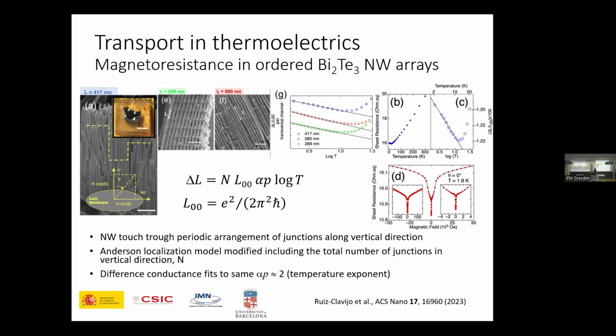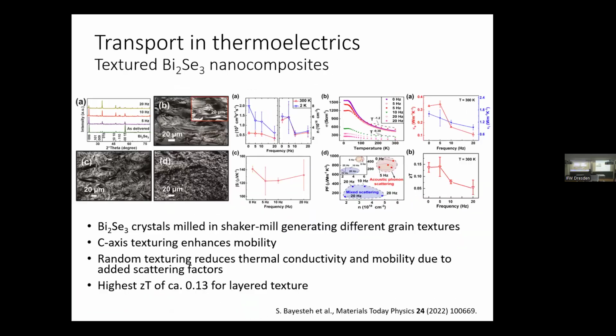And then the more natural question for me would be, if you're speaking again of grains and grain boundaries, what about topological surface states? Yes, complicated. This is not included in here. In this summary, there is some effect. It should be topologically protected. Well, these materials are extremely disordered. So we did not measure flakes of these things; nanolayers have been measured a million times. But nonetheless, it's not presented here. It's measured, I can show you later in the discussion. We can see localization effects in these composites. Localization with the surface or the boundary? In the whole thing.